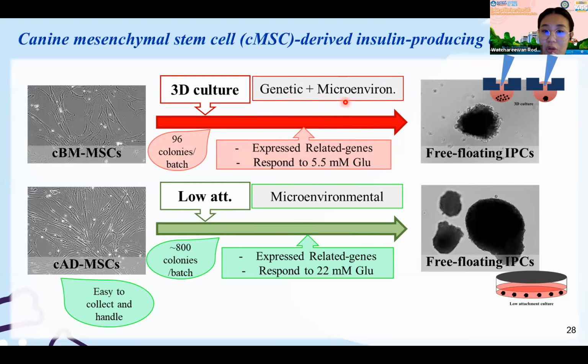And moreover, this protocol also requires 3D culture. What is the 3D culture? The 3D culture, or what we call the hanging drop protocol, is where the cells are seeded in a system that creates a water drop, and then the cells accumulate and form the colony inside that water drop, and we do not let the cells attach to the culture dish. From this result, we found that one time we are only able to produce just 96 colonies of IPC, because the system is a 96-well plate. So if you need a lot of colonies for transplantation, you need more plates to produce them.